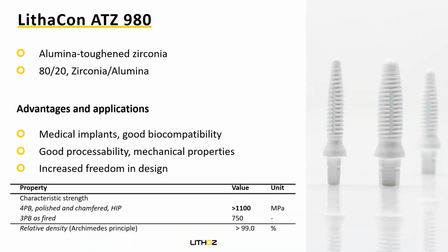The next one I want to show is LithaCon ATZ 980. So this is an ATZ, an alumina toughened zirconia with a ratio of 80:20 between zirconium oxide and aluminum oxide. This is also a material great for medical implants, but also for technical applications. The processability is very good, and the mechanical properties, if processed correctly, are outstanding.